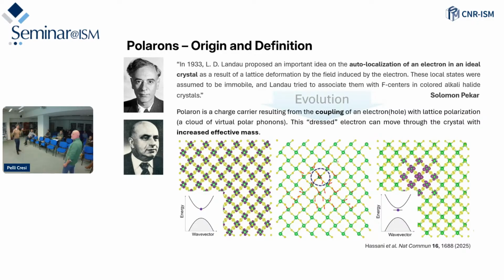The problem is that those are classic polarons. What do you mean by classic polaron? Usually you can study a polaron when you introduce a defect in your structure and you have the localization of the charge. In our case, we study photoinduced polarons, which are related to the fact that you excite the material and you have this autolocalization from the conduction band.